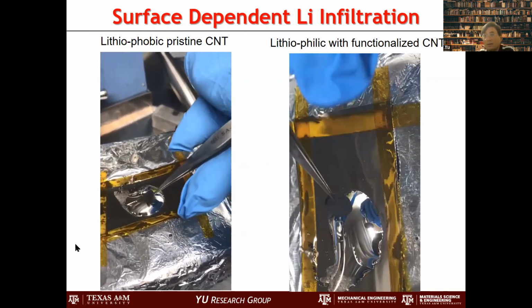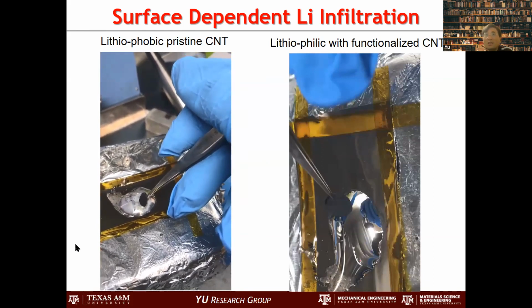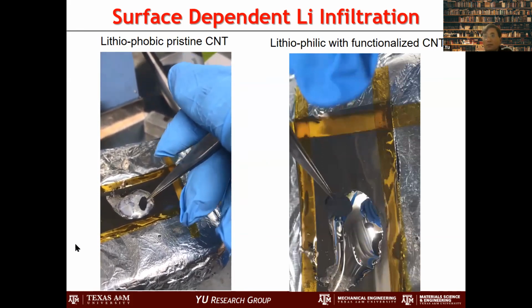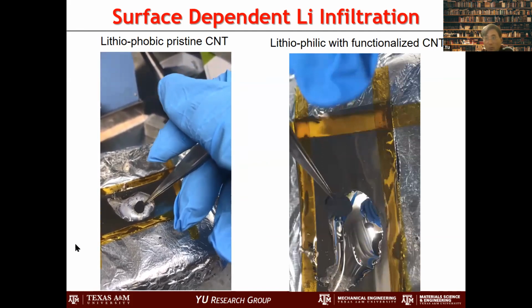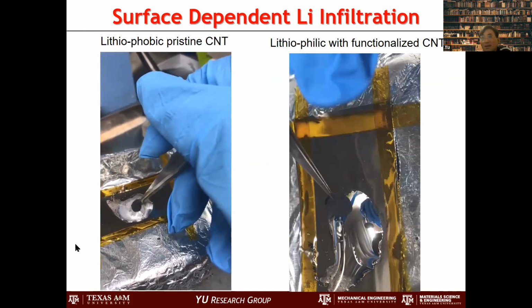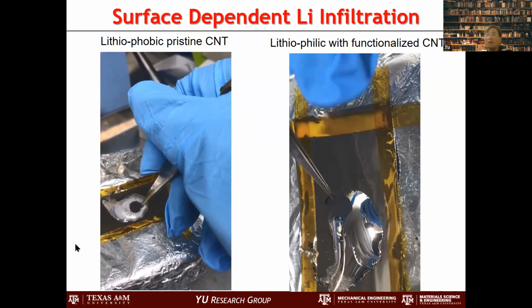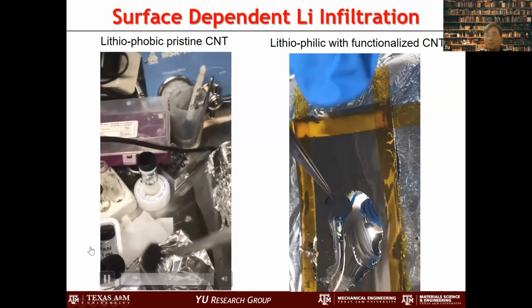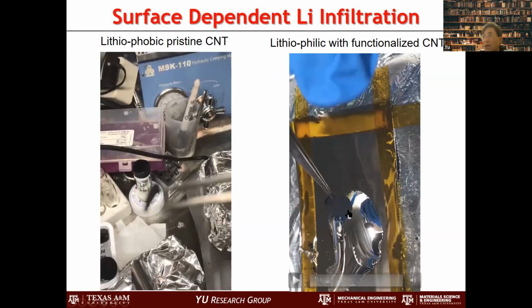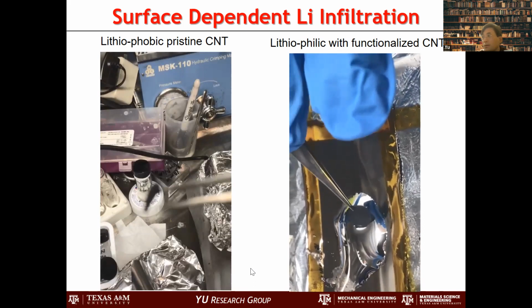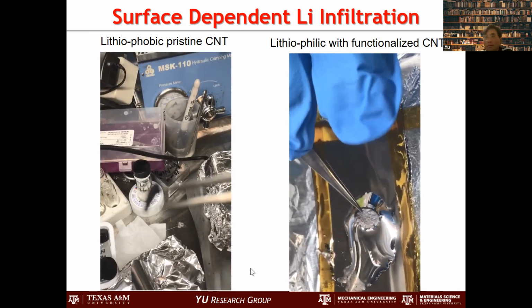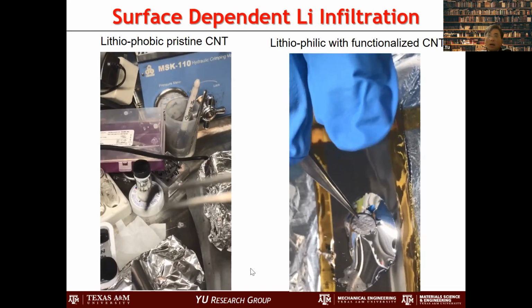So we try to infiltrate. We see that it doesn't get in. Lithium actually doesn't go in. It's pretty stubborn, and they're not getting in. Even if we press it, it doesn't get in. So carbon nanotube, pristine carbon nanotube, doesn't like lithium. But when we actually functionalize with this functional group, and as you can see here, we just touch it, and it starts to wet and get in. So the functional group on the surface is so important, and so that we can change the property dramatically, like this.